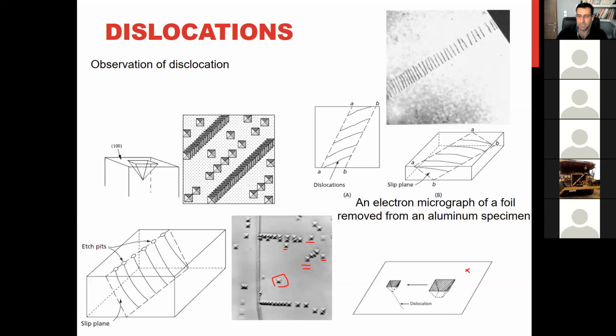When you have a polished surface of a metal sample and you put it in the acid, a pit, something like this, will form. And this is nothing but a dislocation. It is another defect we see inside the metallic material that comes to the surface. When it comes to the surface, around this dislocation we have higher energy than other parts of the metal. So if around it is a corrosive medium like acid, this will be corroded and a pit will form, like this.